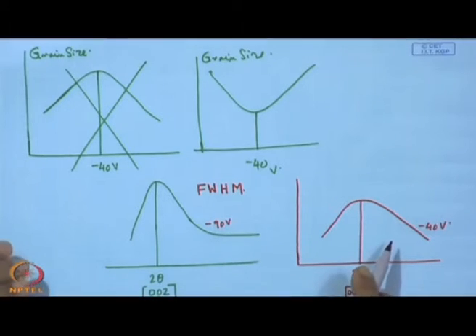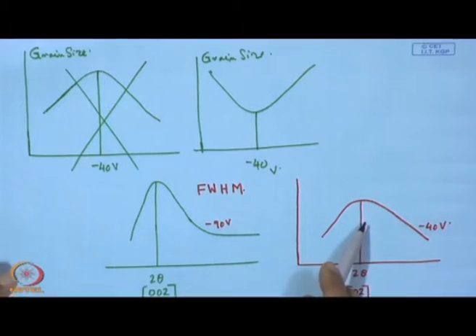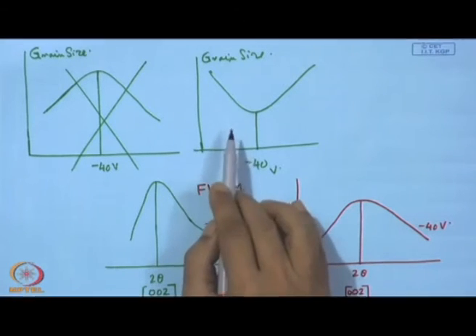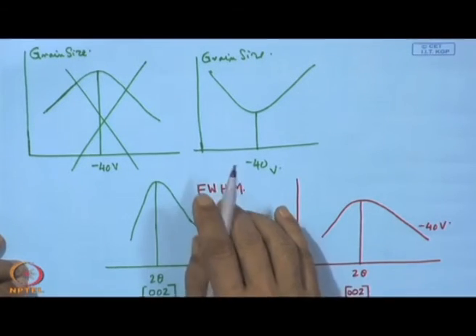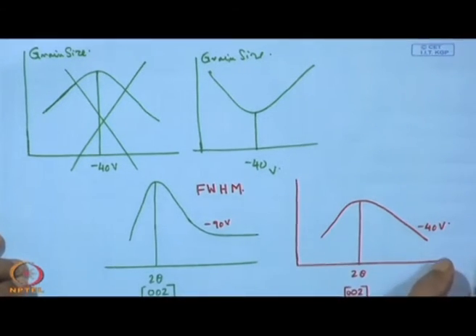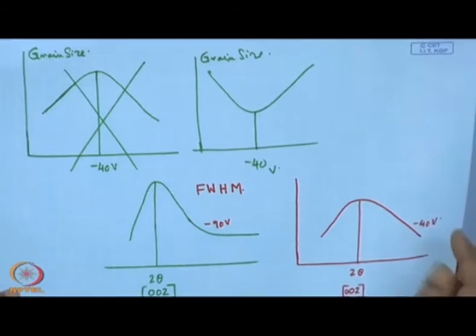So, from this X-ray diffraction diagram, one would be able to locate the condition around which the grain has the finest or smallest size. So, this grain size refinement is also the result of this substrate biasing.